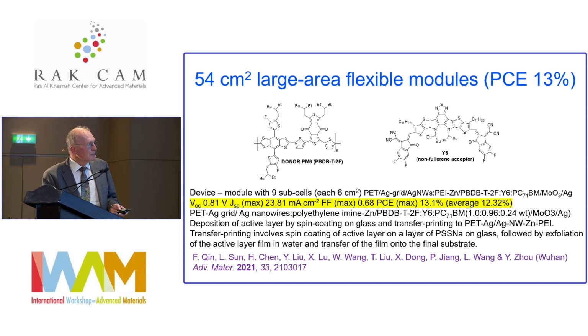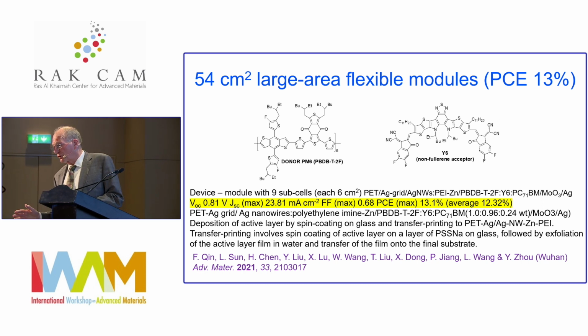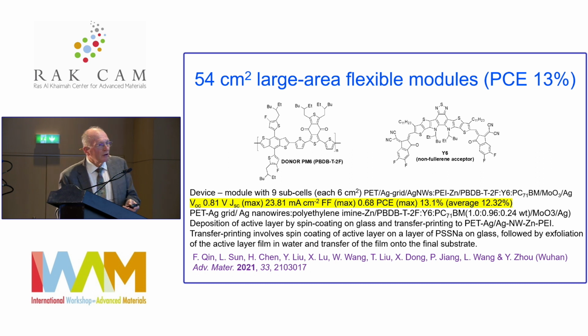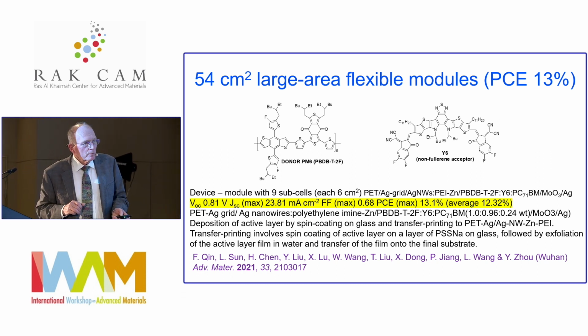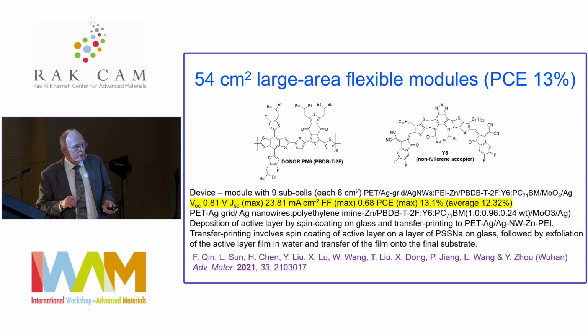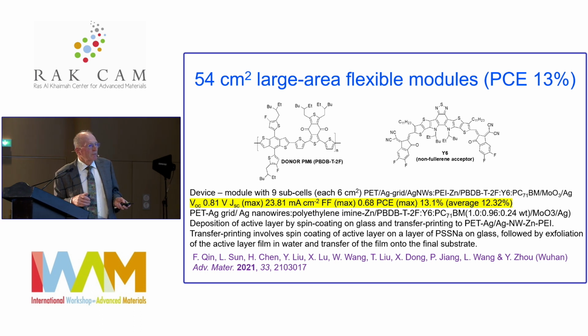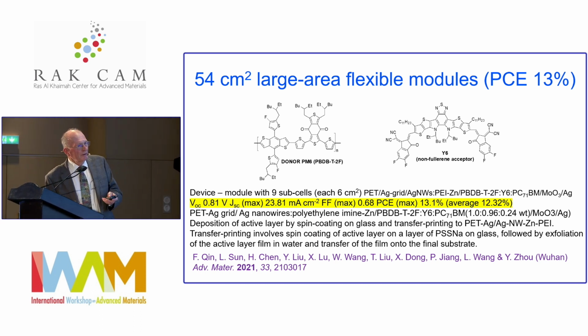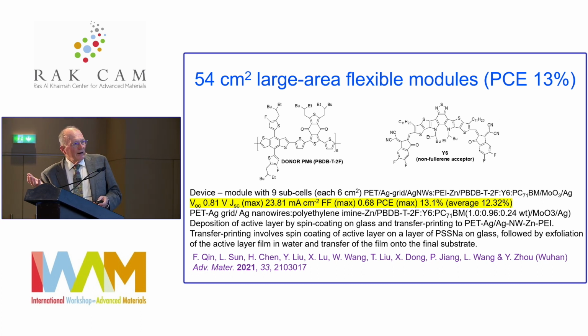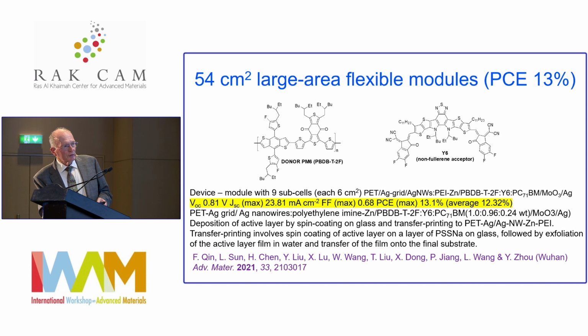And they did deposition, first of all, by spin coating on glass, which is not a large-scale manufacturing technique, the combination of the PET silver grid with silver nanowires and polyethylene imine. They put that on glass, then they assembled the remaining parts of the cell from the right to left onto a flexible polymer device, and then they printed the stuff on glass by putting it into water and floating it off on a layer of polystyrene sulfonate sodium salt. And that exfoliated layer was then transferred onto the final substrate to put the top electrode configuration.